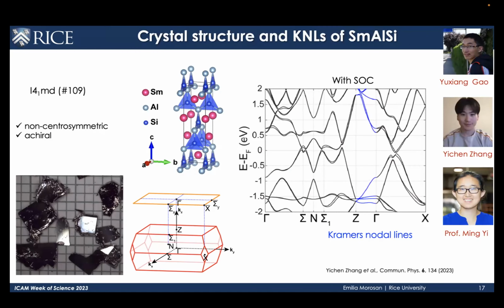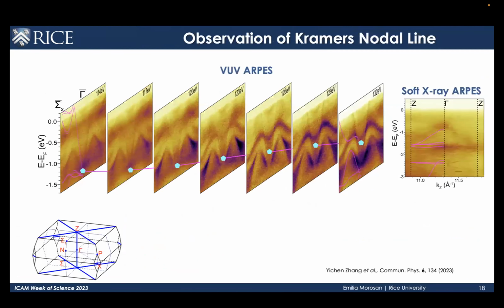I should point out that this degenerate line is along gamma Z, and if we do cuts in ARPES in the orthogonal directions along the gamma sigma X, as the energy changes, you see this point moving up at the gamma point. And then comparison of soft X-ray ARPES with calculations showed these Kramers nodal lines and good agreement between ARPES and theory.